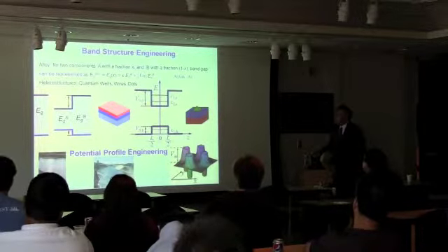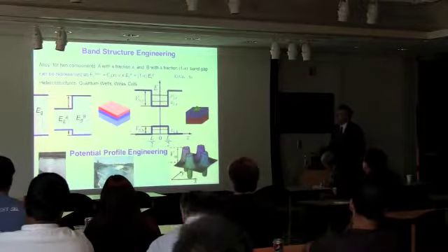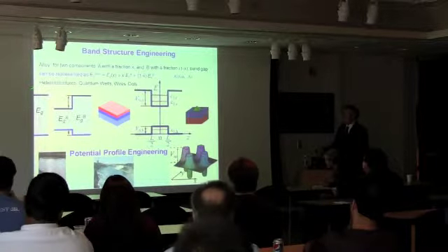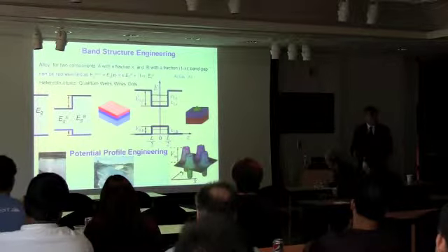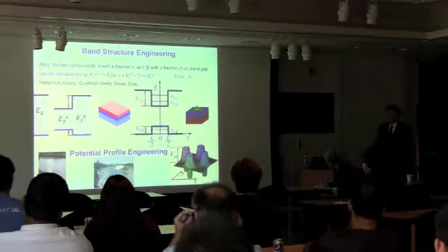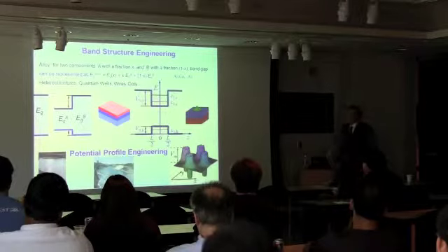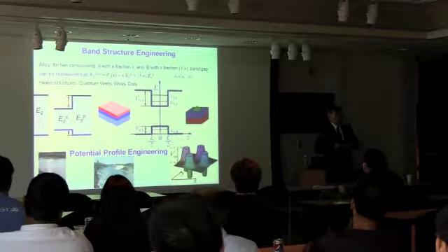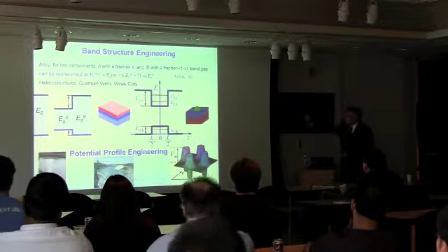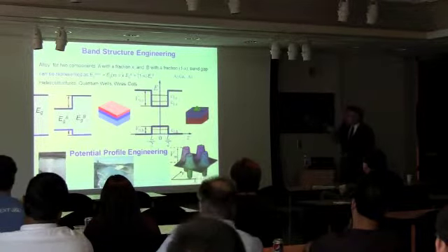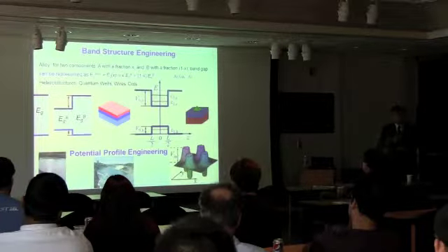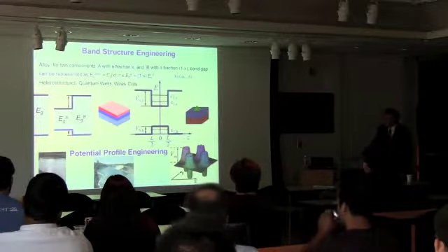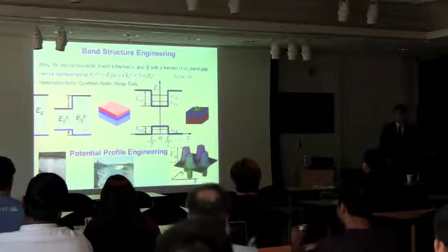Then of course I can move the material, again B or C, and close this. It will be like, for example, thin films. And this thin film between two other materials gives me the opportunity to have a so-called quantum well, if the material that I'm interested in is very thin. So now I have two-dimensional systems. Electrons can move only in the plane because this is a very thin material.